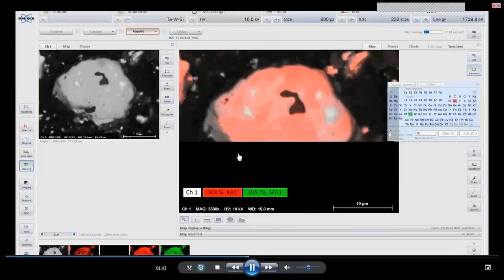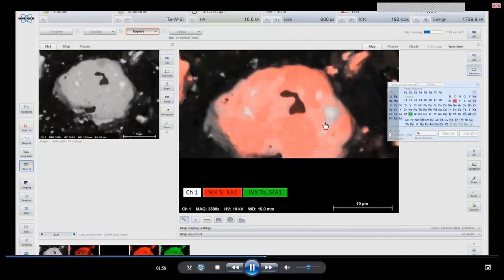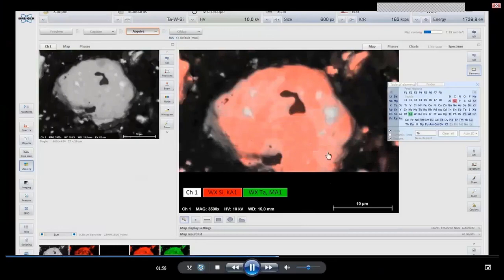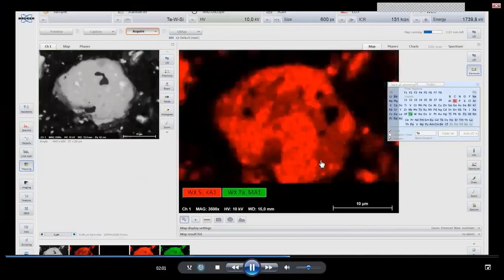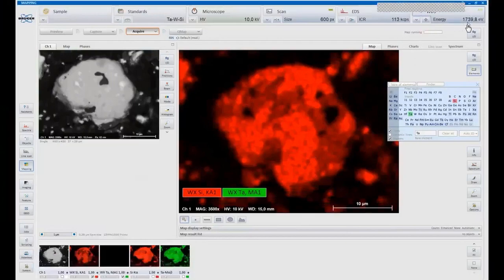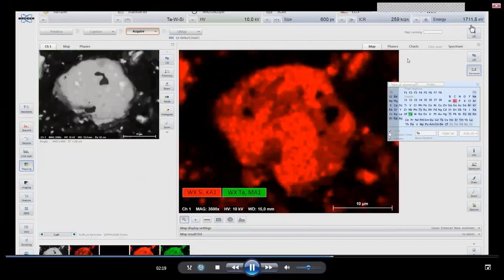We're seeing the particle with the inclusions where we don't see any silicon. So this is void of silicon, and we see a patchy distribution of the silicon within this particle. We are almost done with mapping of the silicon. Now we skip the BSE image, so we only see the X-rays for the silicon. We see the patchy pattern. And you will see here the energy will be switched now from silicon to the energy of tantalum.